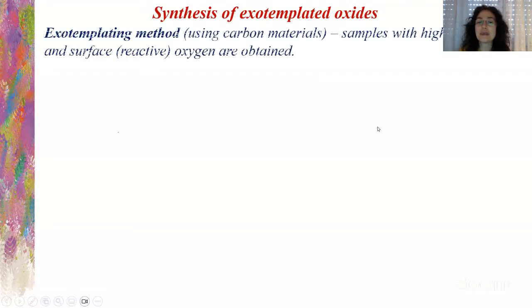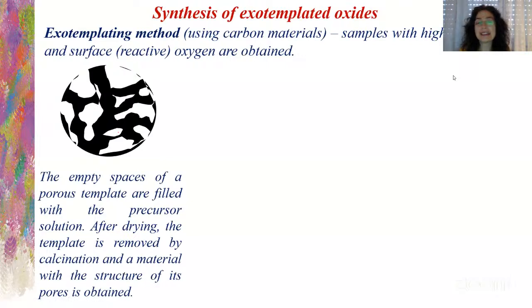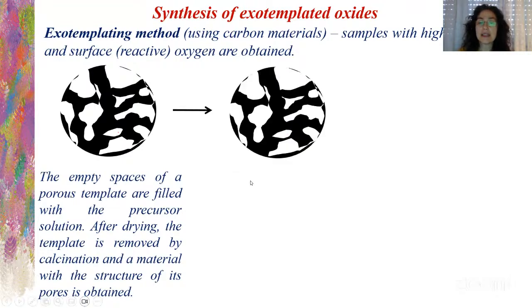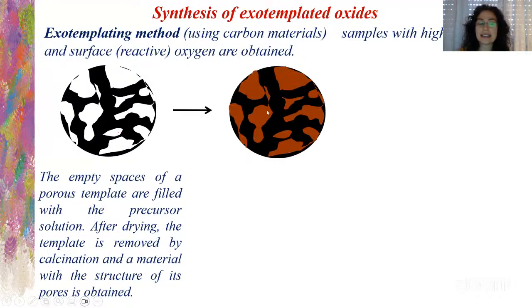But metal oxides can also be obtained by other methods, like, for example, exotemplating. So in the exotemplating method, in this case, I used carbon materials with a high surface area and surface reactive oxygen. So how does this work? You see, we have here a porous template, a carbon template, and the empty spaces of this porous template are filled with a precursor solution. So that means we fill it like this.